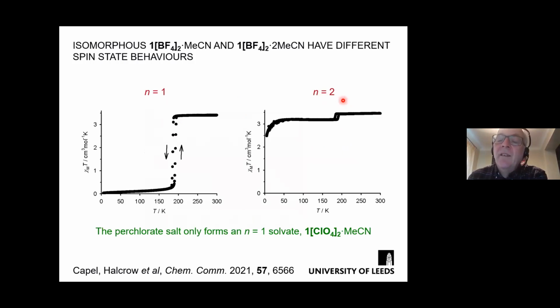The N=2 solvate is high spin. It loses a little bit of solvent inside the SQUID. We make a little bit of this stuff, but it's high spin during the measurement. The N=1 solvate with less acetonitrile shows a nice abrupt spin transition here.